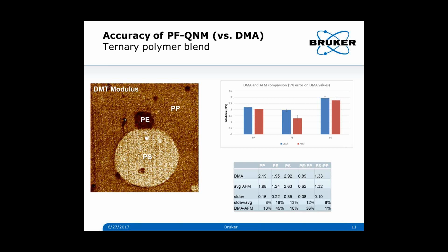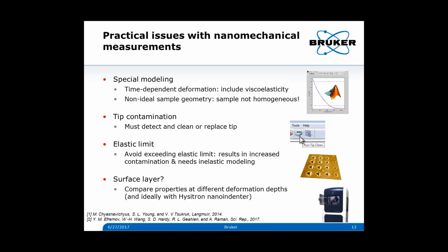But the question arises, why doesn't the polyethylene match the DMA results? And we know the system is calibrated really well, so something is going wrong with the modeling. Possibly the adhesion is the issue, as Dalia mentioned earlier. Maybe we did all the fitting with a DMT model, but it could also be related to the viscoelasticity. This really comes down to the fact that in some cases you need to use special models in order to get the accurate intrinsic properties of the materials.